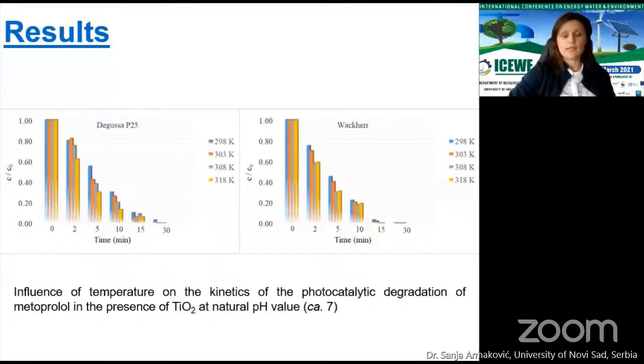Higher temperature than 298 Kelvin or 25 Celsius degrees contributes to increased degradation efficiency in both cases. After only 30 minutes, metoprolol was completely removed from solution.